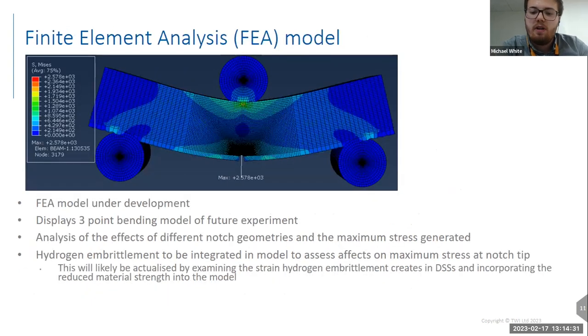As I just mentioned, testing will begin with a three-point bending model, such as the one above, which was made in Abaqus. The model will be used to analyse the effects of changing notch geometries to find an optimum notch geometry for physical testing, by testing multiple notch geometries and assessing how they affect the maximum stress at the notch tip. Further development of the model to include hydrogen permeation will likely be actualised through examining the internal strain created by hydrogen embrittlement and incorporating the reduced ductility and strength into the model's calculations.